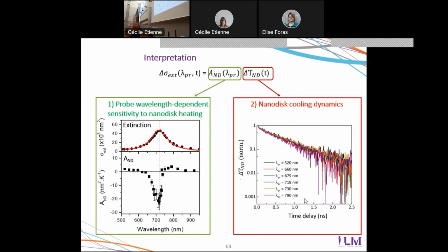In this situation, our signals are just proportional to the evolution of the nanodisk temperature. So it's almost perfectly exponential decay times a coefficient which represents the sensitivity of the optical response of the nanodisk to its heating. So, as time goes, I will very briefly discuss the two aspects.